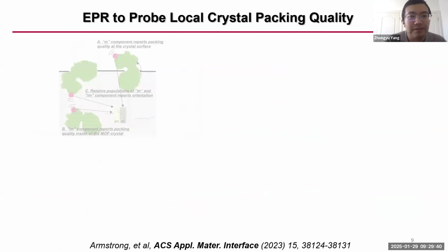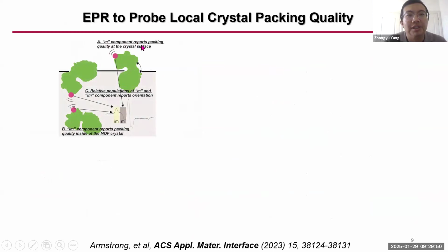So now the EPR comes into play. I told you how we can distinguish the exposed and buried site. And in fact, if we look at the mobile component, it not only tells the local motion of the labeled site, but also tells you the packing quality at the crystal surface. And inside, right, the immobile peak not only tells how restricted the labeled site is, but also tells you the packing quality inside of the MOF. And of course, the relative population tells you how much is exposed.